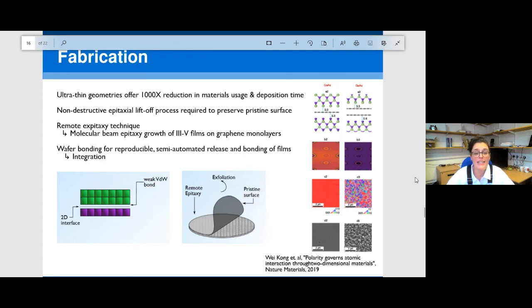And one of those is remote epitaxy. So that's essentially using a 2D layer which is positioned between a substrate and our epitaxial film. What that does is it allows the registry information from the underlying substrate to permeate through to the epitaxial film and allow that crystalline growth. But what you don't have is the bonding between the film and the wafer. So in theory, you can then peel it away. You can just exfoliate it away, which would be great news, wouldn't it? That's the story. We've developed this at the wafer scale, and then we have a pristine surface for regrowth.